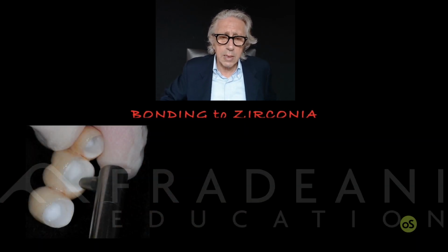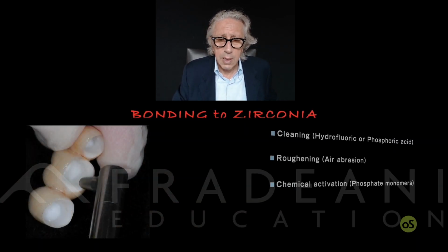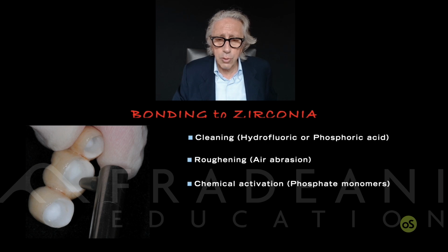So how to bond zirconia, that is not an etchable material? The literature that you can find around can show you that you need to clean the inner part of the ceramic. Some people say not with the phosphoric acid. That is quite a controversial issue. Anyway, you can roughen with air abrasion, 50 microns of alumina, sandblasting material, and then you have to use, that's the most important difference, a kind of phosphate monomer inside the cement. You can add it, or you can have it inside the cement. This is called a chemical activation.